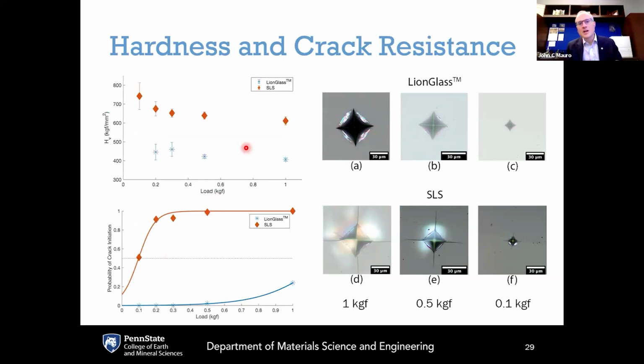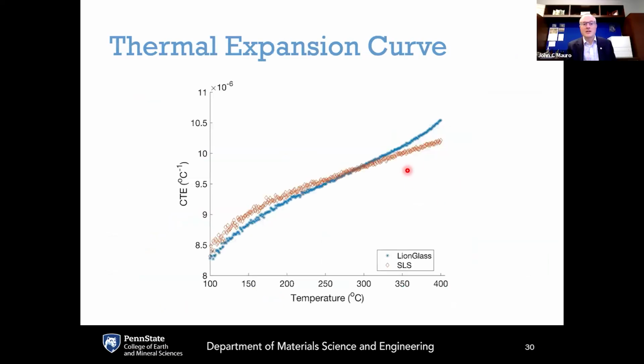This graph shows you some more details about the improved mechanical performance of Lion Glass on top, compared to soda lime at the bottom. You can see the Vickers indents here of soda lime at 0.1, 0.5, and 1 kilogram force, and the cracks that pop in here with soda lime, and the cracks that are not popping in here with Lion Glass.